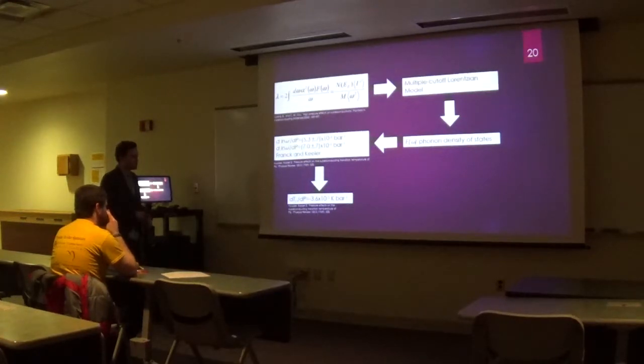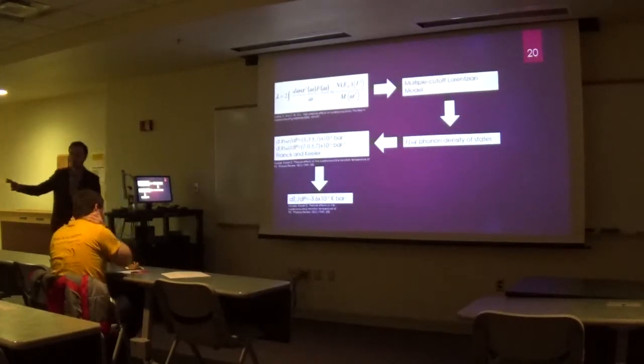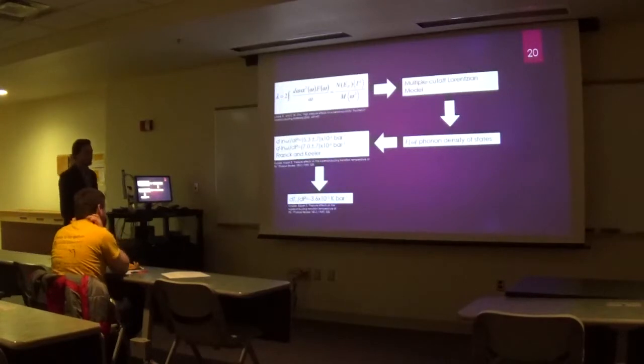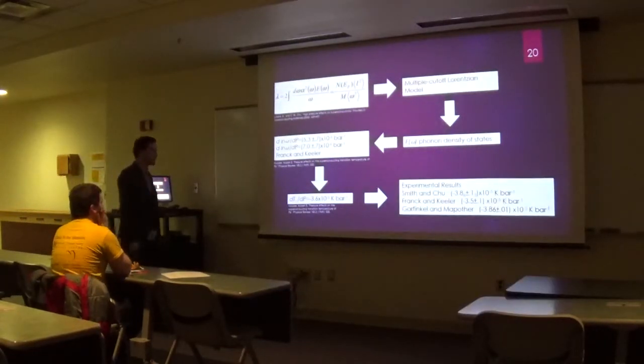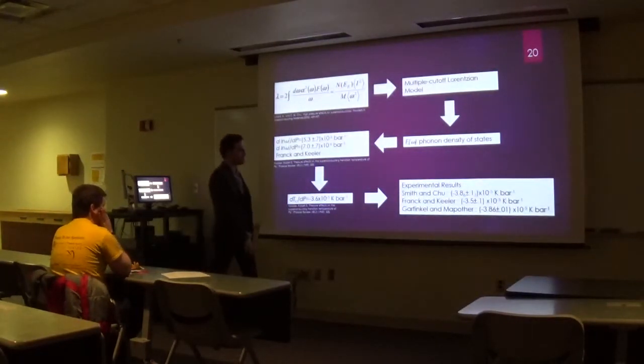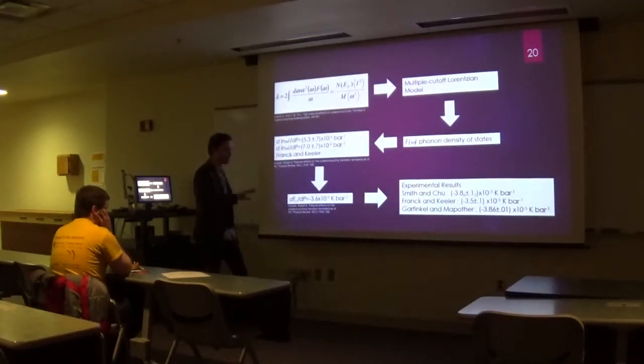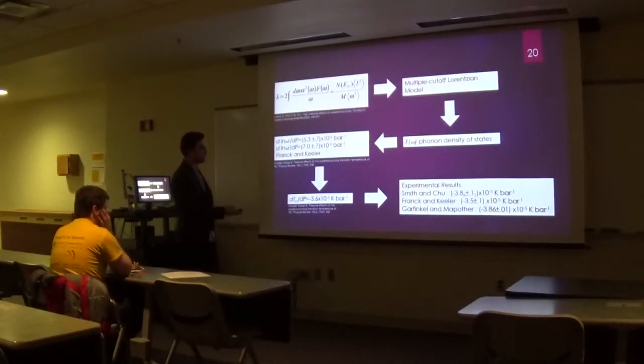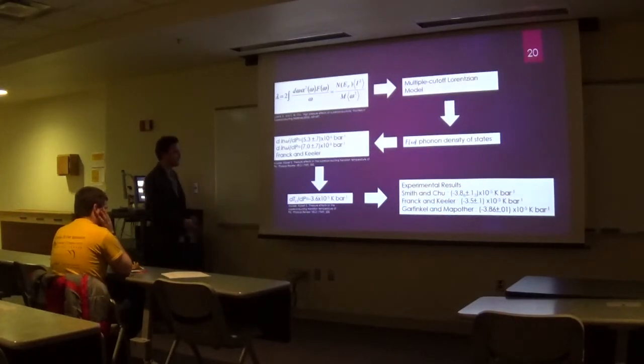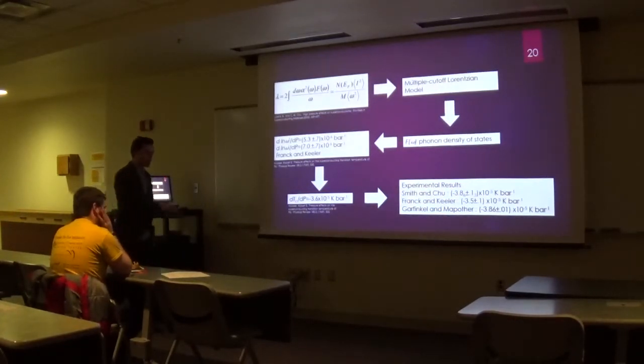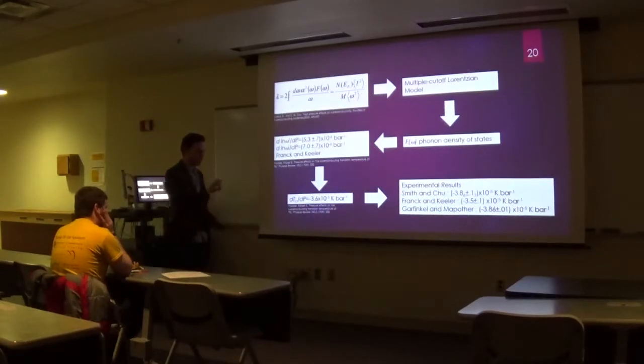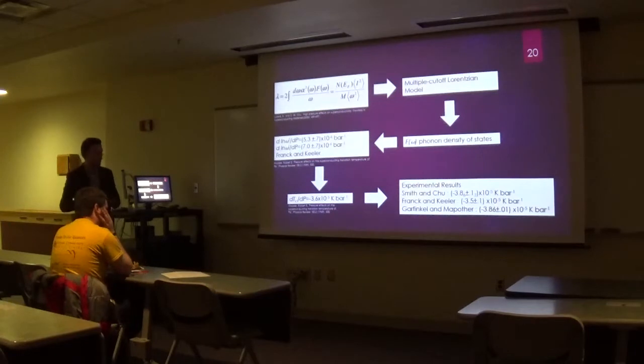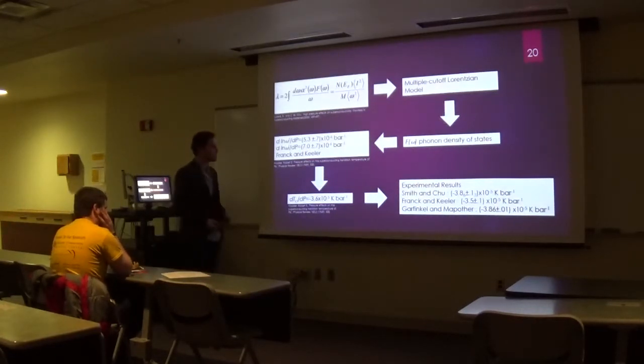So this was a theoretical approach. How does this work when compared to experiment? It actually works pretty well. This is just data from three different papers. The Smith and Chu one was from the pressure coefficient earlier. What this shows is that yes, our theoretical assumptions hold, and if we're only accounting for the change in our phonon frequencies, this is one of the main driving factors in decreasing our critical temperature.